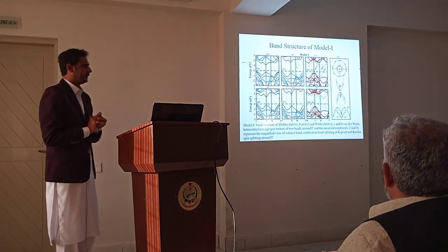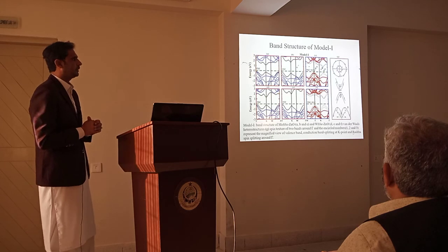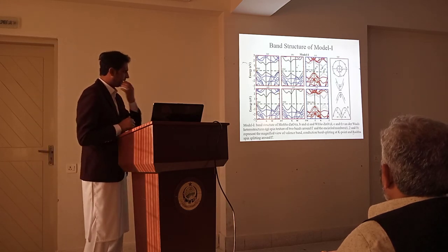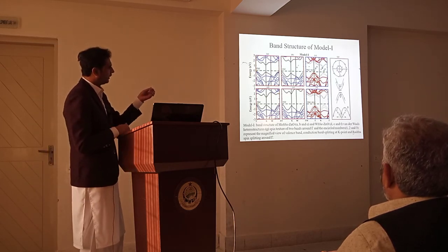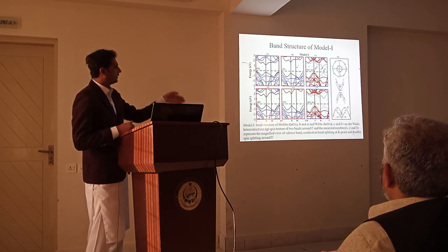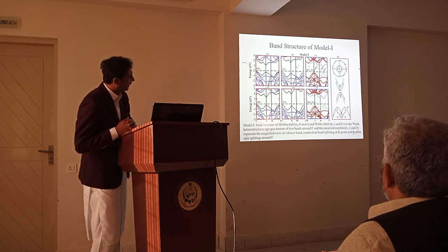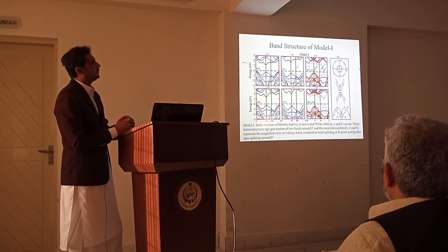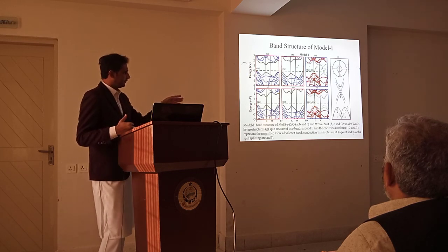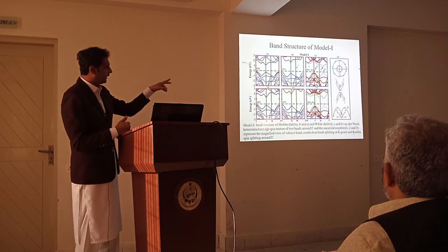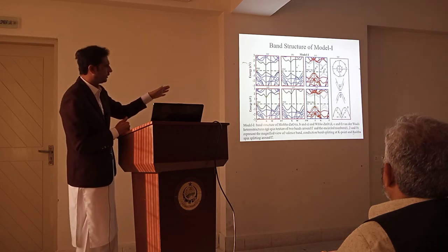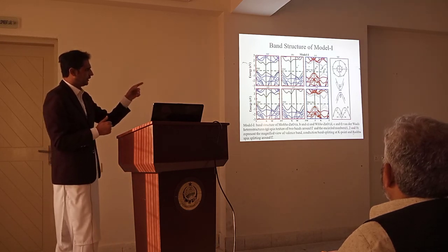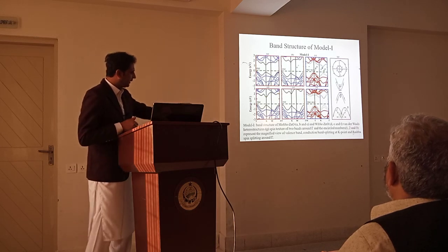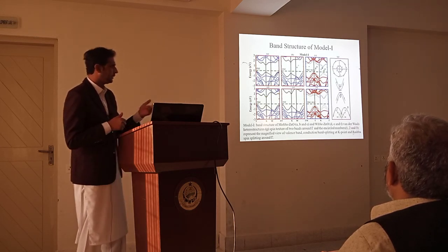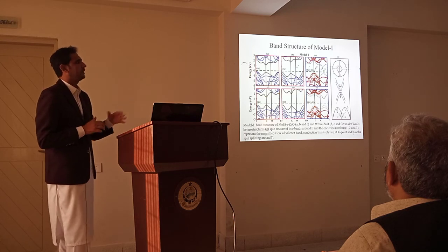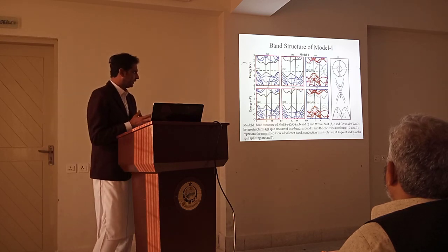This is the calculated band structure for model first. Here the black color represents PBE. Here the first one is for PBE, the second one is for HSE, and the third one is for PBE plus SOC. All these materials are indirect band gap in nature. Here the CBM is at the K point, while the VBM is at the gamma point of the first Brillouin zone. Similarly, for HSE, only the band gap increases.